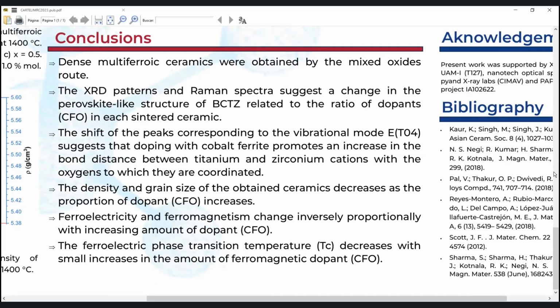The density and grain size of the obtained ceramics decrease as the proportion of dopant increases. Ferroelectricity and ferromagnetism change inversely proportionally with the increasing amount of dopant. The ferroelectric phase transition temperature decreases with small increases in the amount of ferromagnetic dopant.